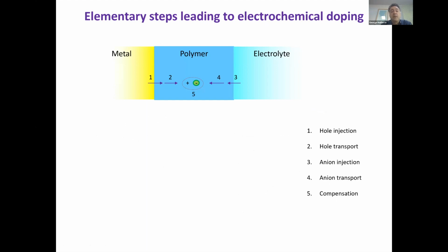So what we propose is that we use the same language for electrochemical devices. For electrochemical doping to take place in a semiconducting polymer, take a polythiophene, put it on a metal electrode, immerse it in an electrolyte. If you apply a potential that can bring anions into the film in order to dope it, the following processes happen. Electronic charge, the hole, has to be injected from the metal to the polymer. It has to be transported some distance inside the polymer. At the other end, an anion has to be injected from the electrolyte to the polymer, transported over some distance, and then the two can compensate electrostatically each other. So these are the elementary processes.